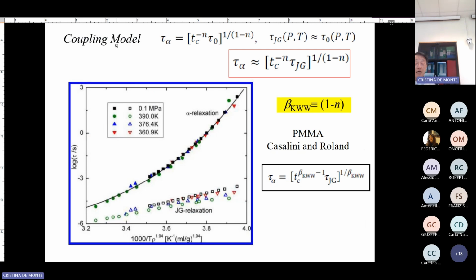You see that? This is done by Casalini and Roland in my lab in Washington, D.C. And so they do PMMA. This is a polymer. And the alpha and beta there. Again, at the bottom is T rho to the gamma, where gamma is about 1.94, so about 2 again. And again, you can scale the whole thing together with the same variable. Again, the JG relaxation has very important fundamental meaning.